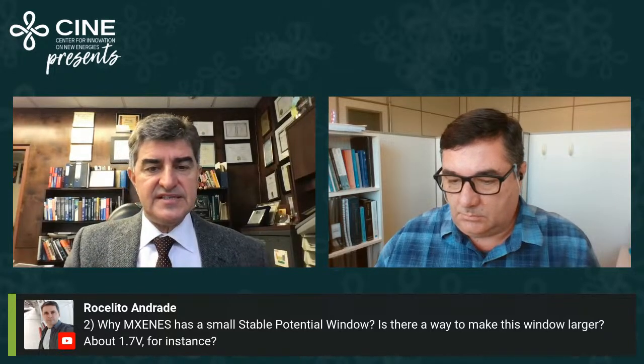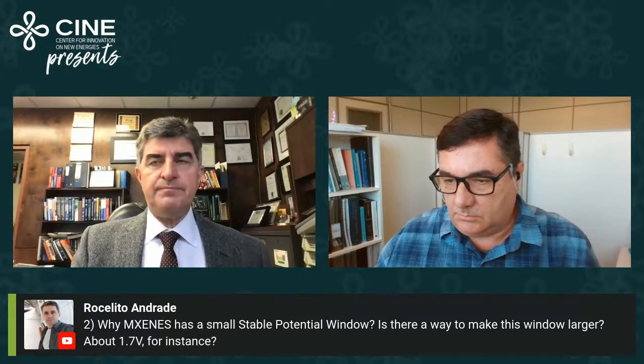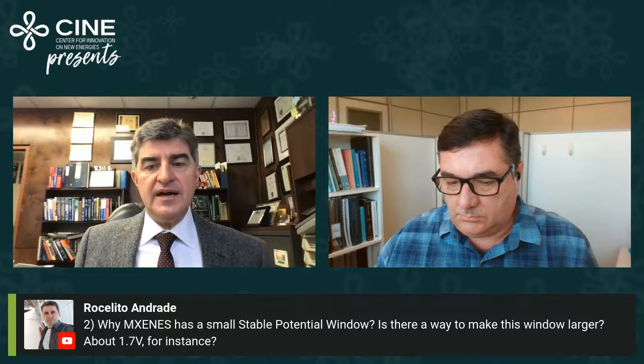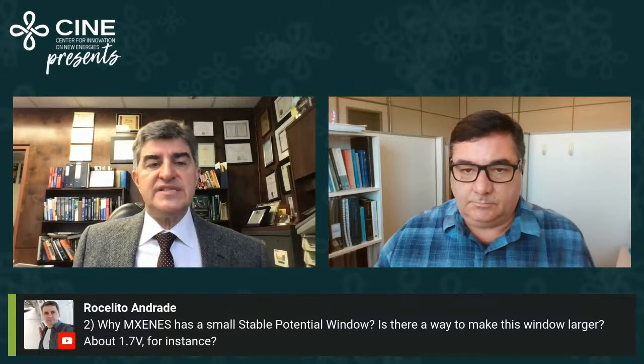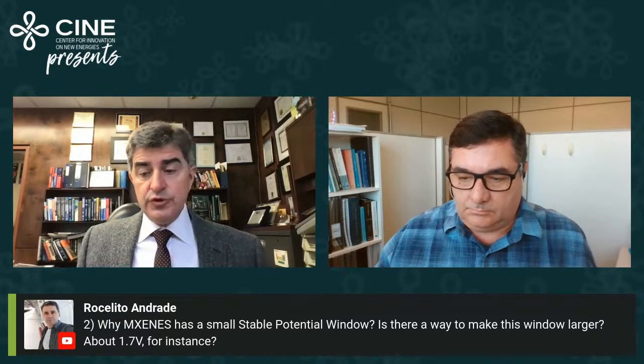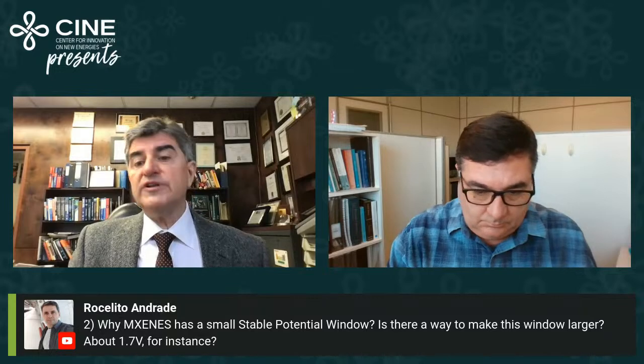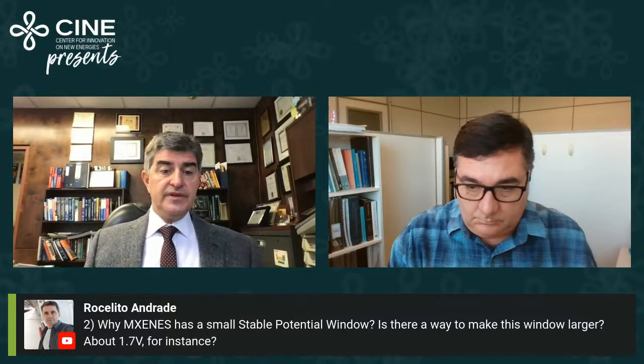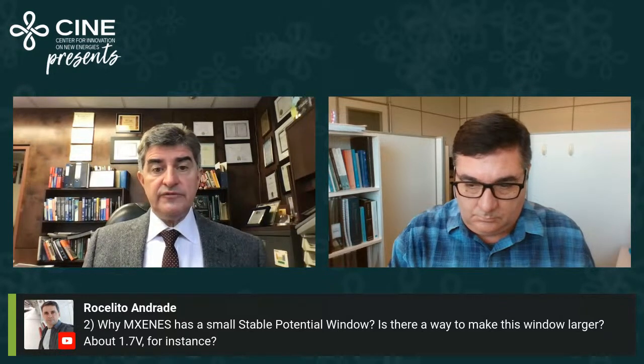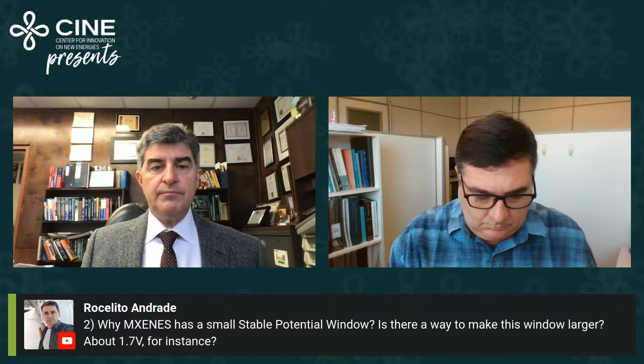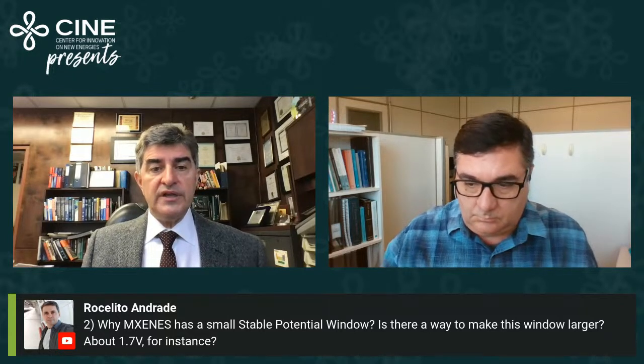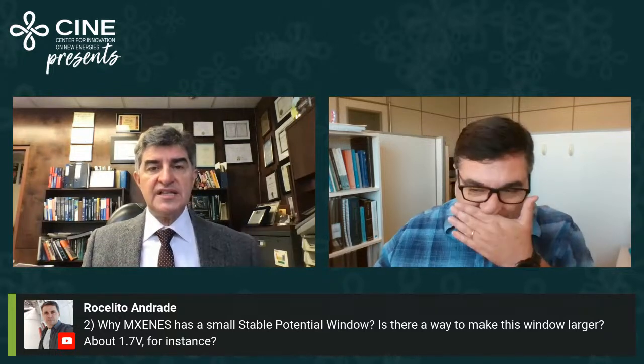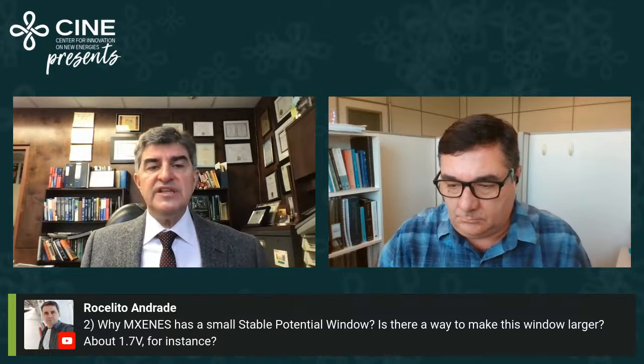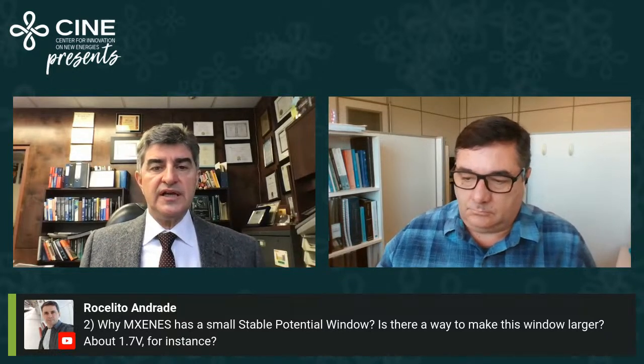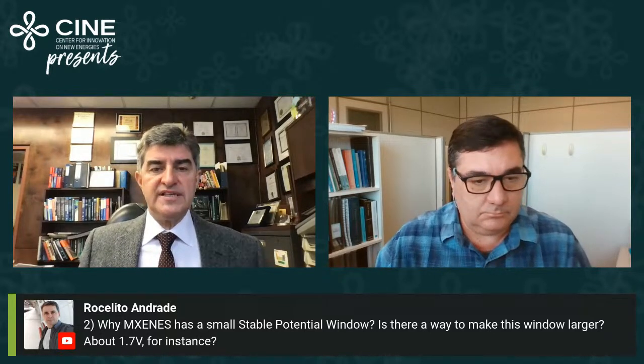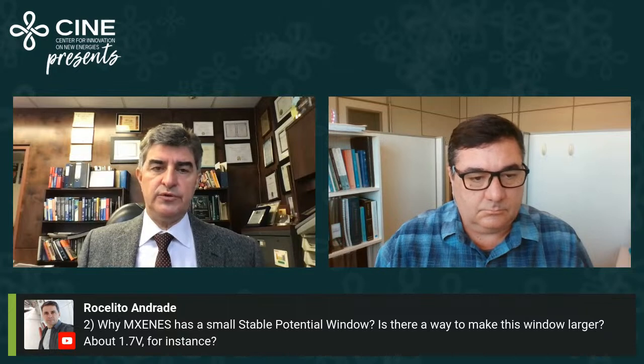When I showed, for example, this here or previous cyclic voltammograms, those are potential windows, say in protic electrolyte, acidic here. If you take, for example, water and salt electrolyte, I have here an extra slide. You can increase the voltage window in, for example, 19.8 molar lithium chloride to about 1.6 volt. So yes, short answer is yes. You need to select MXene, but also it depends on the electrolyte, of course. So in aqueous electrolyte, but saturated or water and salt electrolyte, you can certainly have a wide voltage window.